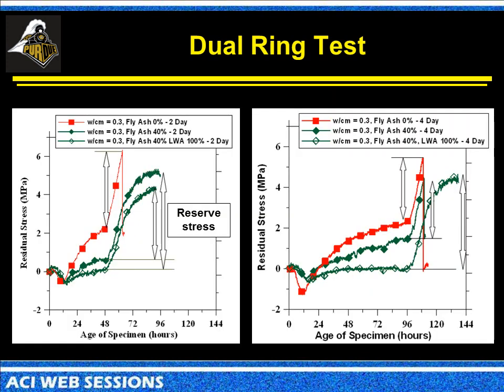Now, if we don't look just at 2 days, we take this out and we apply the temperature effect after 4 days, we can see that we've got some residual capacity in the plain system. The fly ash system is starting to creep up there. We've got some residual capacity, but we're now able to crack it at about a 16, 17 degrees Celsius temperature change. But the mix with internal curing, we're keeping the autogenous shrinkage low so that even when we change the temperature, we drop it from 23 degrees down to -5, we still haven't cracked the system.